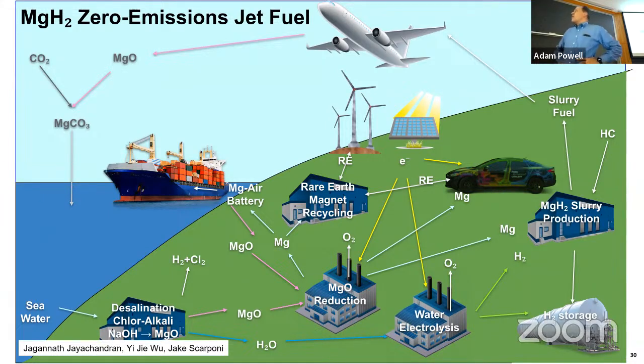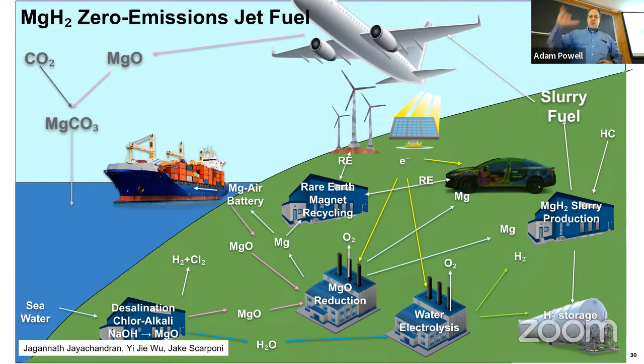Right, so what do you do? Well, let's think about metals, and there's the graphs that I'm showing of energy density and specific energy. Those came from a paper that Jagan found. And maybe metal hydrides. So we came up with a mixture of magnesium hydride and hydrocarbon fuel. Part of the inspiration for that came from a company called Safe Hydrogen, which is using a magnesium hydride mineral oil slurry for hydrogen storage. So you heat it up, and the hydrogen comes out. You heat it up under high pressure, and the hydrogen goes back in. But what if we just took this slurry and burned the whole thing? So kind of a crazy idea, not using mineral oil, but using a lighter hydrocarbon.